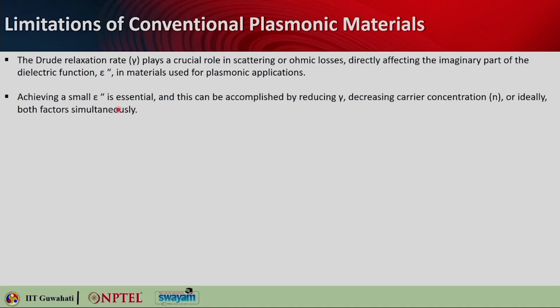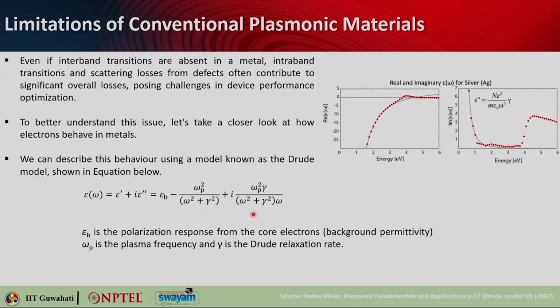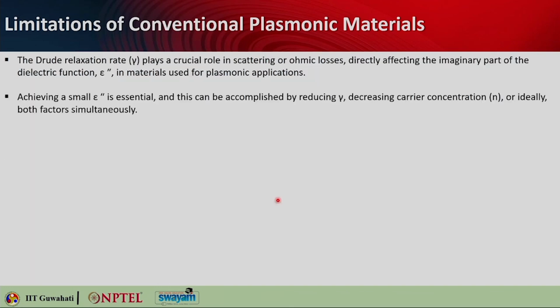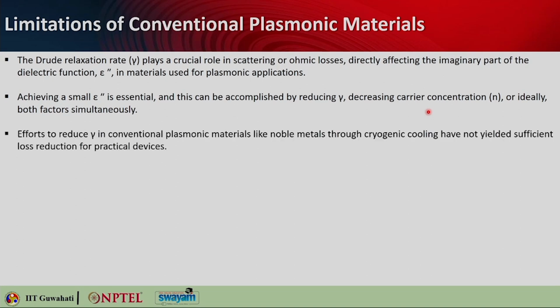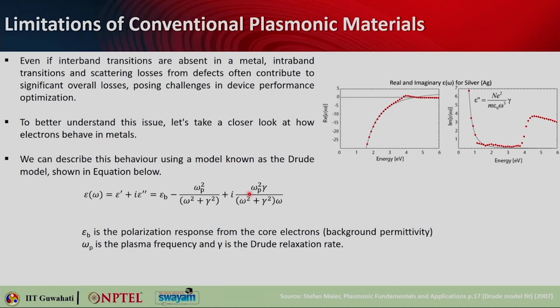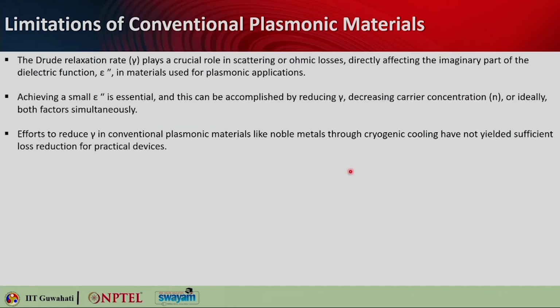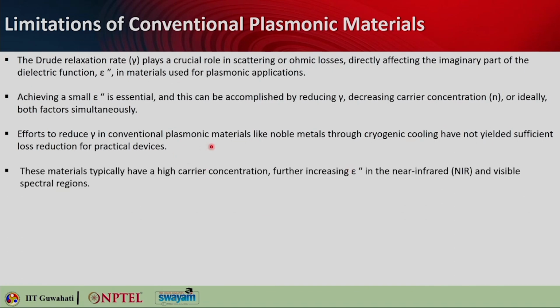Now, if you want epsilon double prime to be really small, then you should reduce gamma, and that means you have to decrease the carrier concentration n, or ideally both. If you are able to do that, that will bring down your imaginary part. Now, the efforts to reduce gamma, the relaxation rate, in conventional plasmonic materials like the noble metals, gold or silver, can be achieved through cryogenic cooling, but that has not yielded a sufficient amount of loss reduction for practical devices. So, that did not work out.